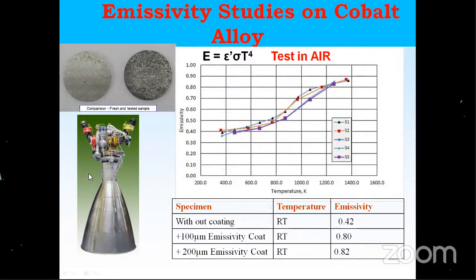Because our engine is going to work in vacuum. In vacuum, the emissivity without coating at room temperature will be 0.42. During actual operation it will never increase beyond 0.5, maximum 0.5, even at 1000 degrees centigrade. This test has been done in air, where oxidation will happen and increase the emissivity. This is your Stefan-Boltzmann law, which says radiated heat is proportional to the fourth power of temperature, and this is the emissivity.